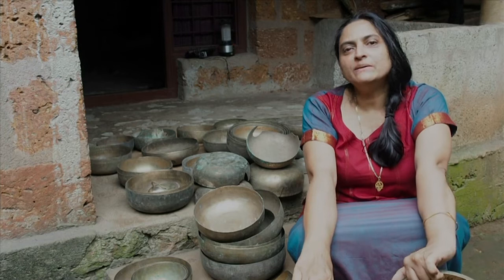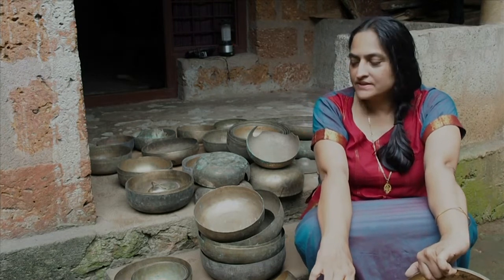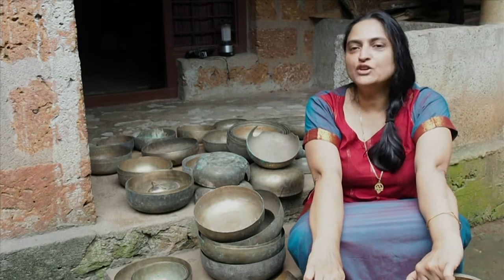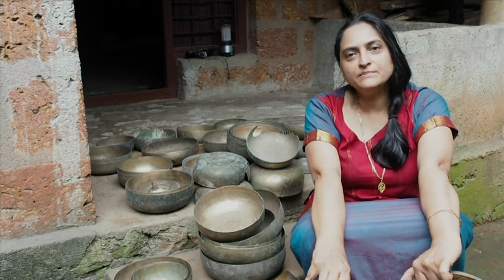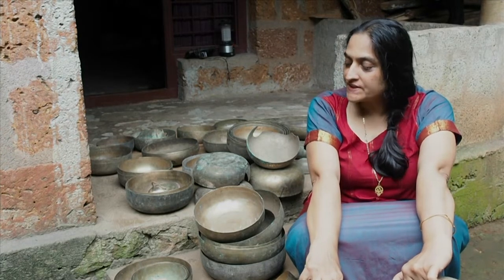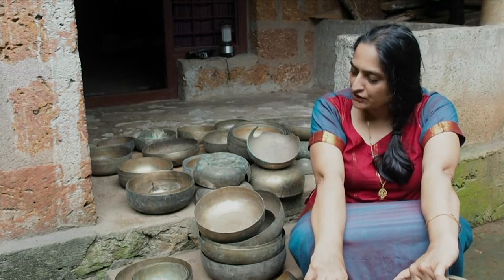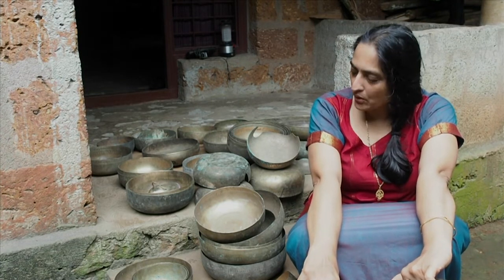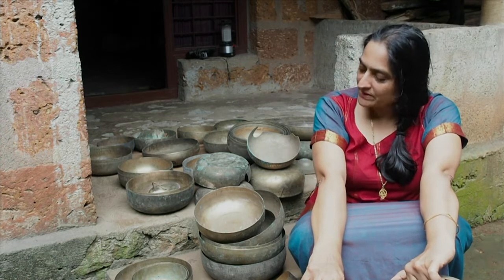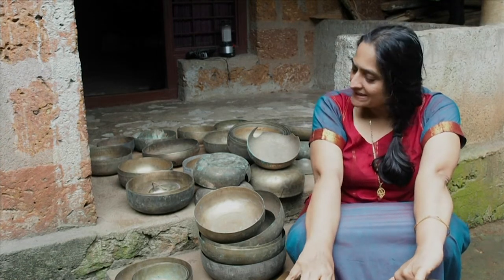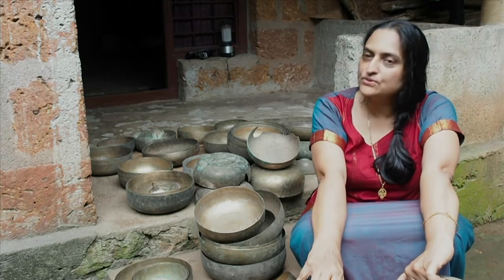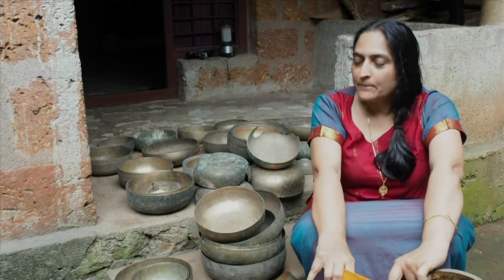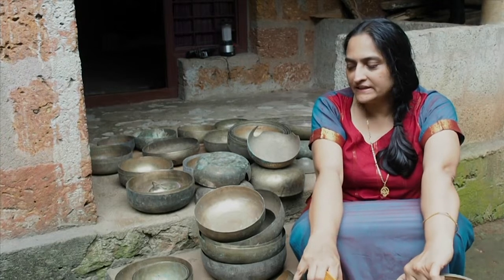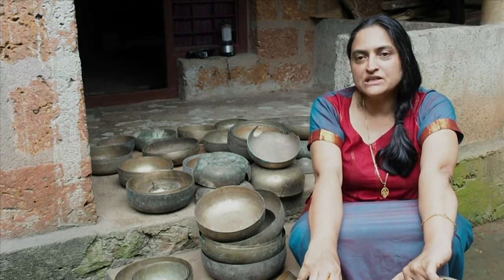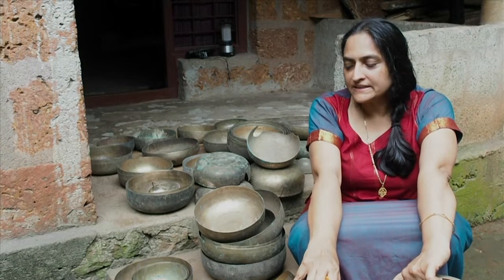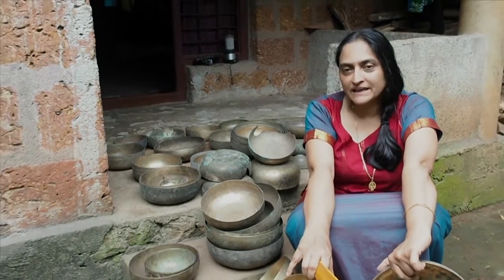It's quite an extraordinary moment for me as an archaeometallurgist. In one sense, as an archaeometallurgist I'm delighted, surrounded by all these wonderful bronze vessels, which are made of a very unusual type of alloy, high-tin bronze, that is copper alloyed with about 23% tin. And this is a tradition which goes right back to antiquity in the Indian context. Back in the megalithic period as well, we find these remarkable high-tin bronzes, especially from southern India, from the Nilgiris and Adichanallur Iron Age and megalithic sites.